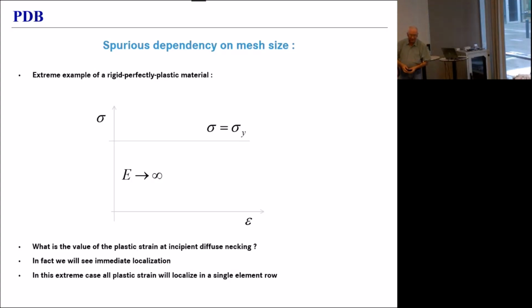Well, it's immediate. You start at 0 because your hardening modulus, which is 0, is smaller than your yield strength. And that happens immediately. So the moment you load, you're going to localize. And this case is actually so extreme that you can try it out in OpenRadioss if you don't believe me. But all plastic strain will localize in a single element. Now let's assume that I can put my hands on some of that material and I do a tensile test on it.